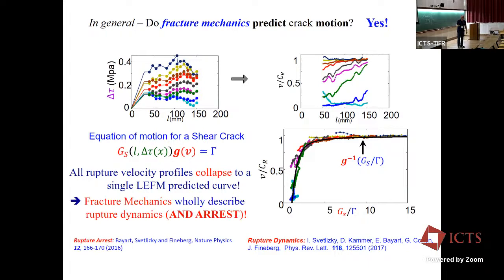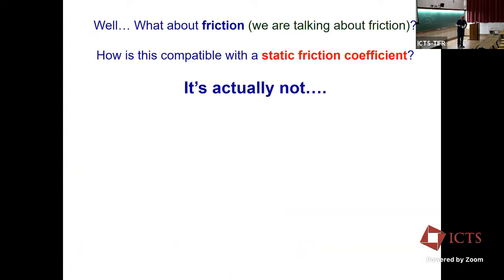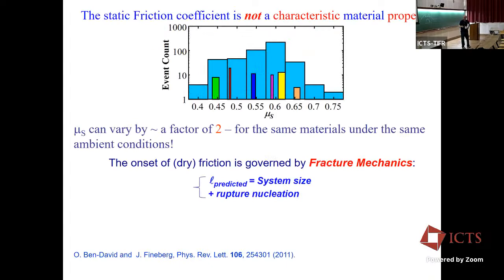Okay, now I have 5 more minutes. Let me just show you the problem that we still have and are dealing with as we speak. So, the friction coefficient, just for fun. These are different experiments with the same plates. This is the spread of static friction coefficients that we measure. Under the same conditions, you get exactly the same static friction coefficient, but it's different from this one. We tilted the plates by 1/100 of a degree.